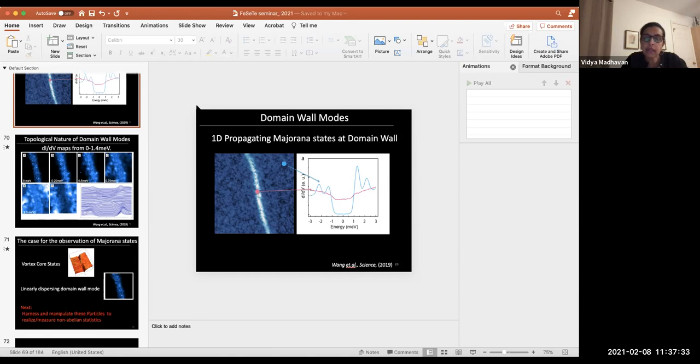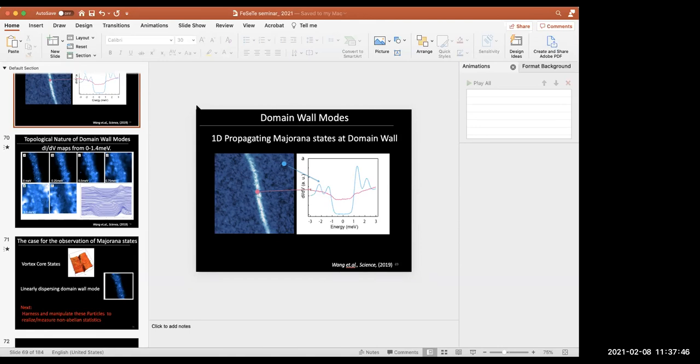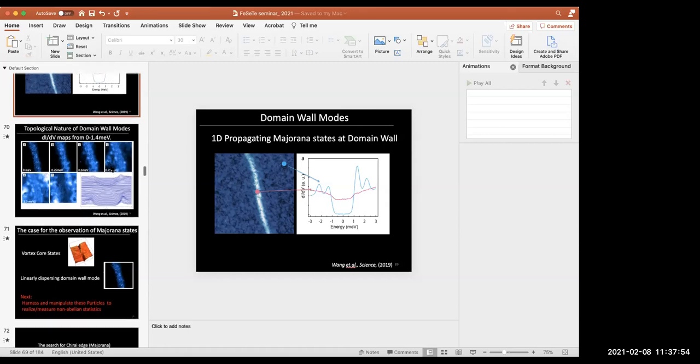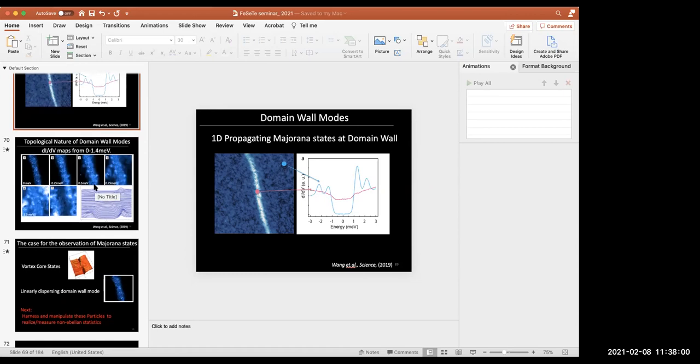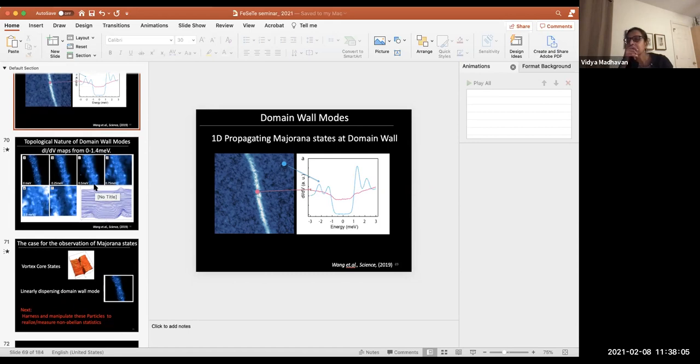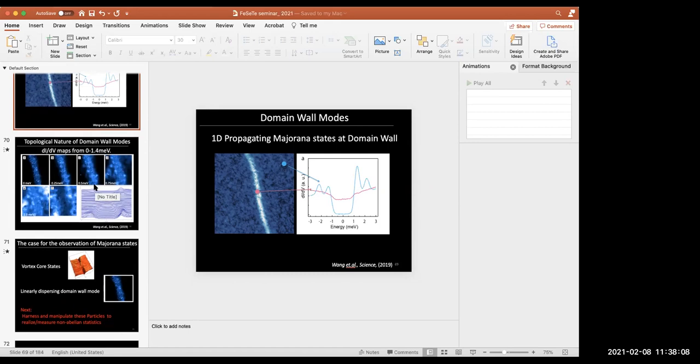All I can tell you is that might be true, but there are a couple of things. One is that would not give me a constant density of states, right? It would give you a non-zero in-gap contribution. Yes, that's right, but not a constant density of states inside the gap. But then you will have broadening. And the broadening, because the odd frequency component will be p-wave, will be smeared considerably by disorder.